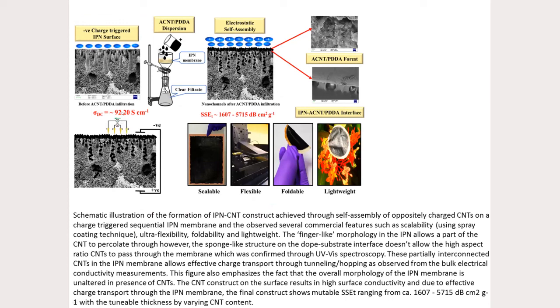So as you can see on the slide, these membranes have a very unique porous structure. So there are pillar-like structures which are called finger-like, and then there is a sponge. And then since we triggered charge, we know the charge on the membrane, and oppositely charged carbon nanotubes were then added, so that now you have a construct where through electrostatic assembly, the CNTs are anchored onto this membrane. And our technology shows that this is scalable. We are able to do this up to A4 sheet size, and it's flexible, foldable, and lightweight.